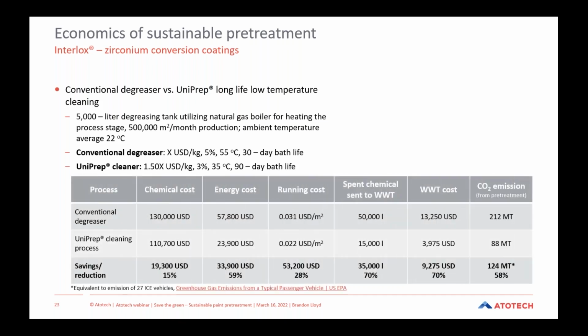So here you can see in this example the different costs that are associated with each of the different steps here. First, starting with the first column, the chemical cost, you can see that with the conventional degreaser, the associated cost of the chemistry is around 130,000 US dollars. And the cost with the Uniprep cleaning system is reduced by 19,300 US dollars, or about a 15% reduction. When we look at the energy cost, reducing the operating temperature from 55 degrees Celsius down to 35 degrees Celsius can have a big impact. And obviously you can see here that we're able to reduce the energy costs by almost 35,000 US dollars per year, which is a reduction of about 59%.